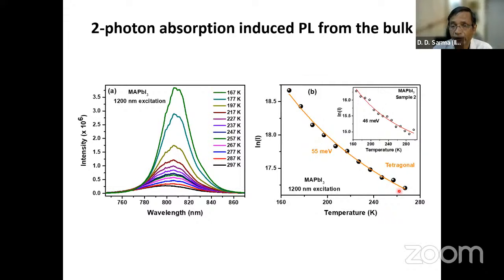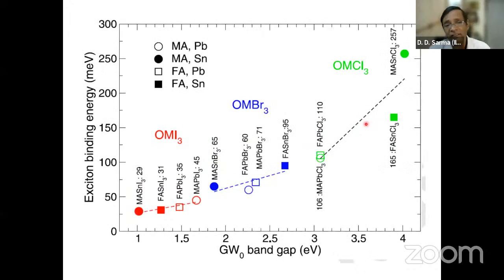Then you can fit it to the equation and extract what the binding energy is. And the binding energies are estimated here. These are the calculated excitonic binding energies you had published a long time back, for many, many compounds. Compared to that, these are the experimentally obtained values, and you can see they are in good agreement with the theoretical prediction we had made a long time back.